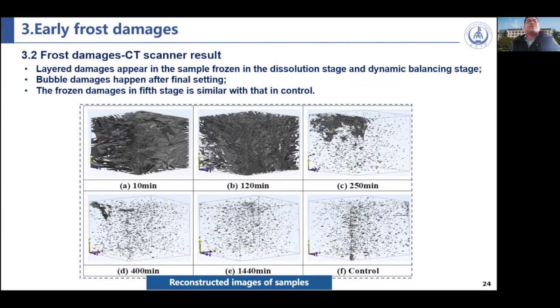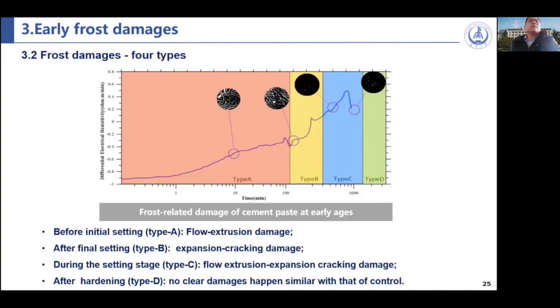This is the control sample. And also these stages combine the layered damage and bubble damages. The frozen damages in the fifth stage are similar to this control sample. So compared with the damages in the cement paste, we summarize four types of frost damages in the early ages.